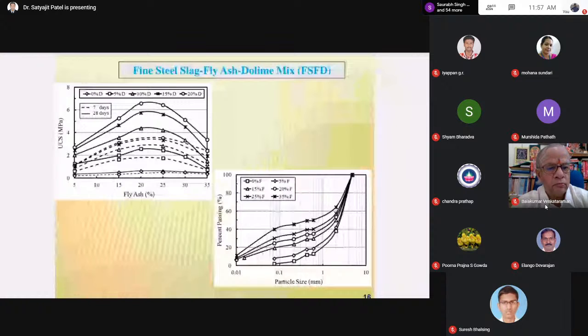So at this fly ash percent of 20 to 25, the strength is maximum. So see the second figure. If you draw the particle size curve, percent passing, for different mixes, for this mix, around 25% of fly ash mix with steel slag, you will get the well graded mixture, SW, well graded sand. So when the material becomes well graded, its void ratio will be lowest. It is well graded, so having particles of all range, so its strength will be maximum. So you can support the argument of maximum UCS value with the help of particle size distribution curve.